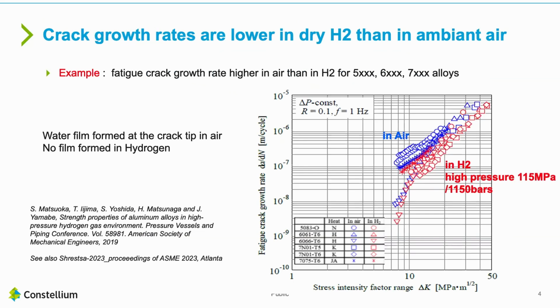Concerning interaction between dry hydrogen and fatigue, we have a few data in the literature. So here is presented data from Matsuoka comparing fatigue crack growth rate in air or under hydrogen with a pressure of 115 MPa (1150 bars). Different aluminium alloys have been considered, either a 5000 series, 6000 series, or 7000 series. As a general view, we have a decrease of fatigue crack growth when the metal is tested under hydrogen versus in air, which is attributed to the water film deposition that can appear in air that is supposed to be a little bit humid, and that was not the case for hydrogen that was dry.